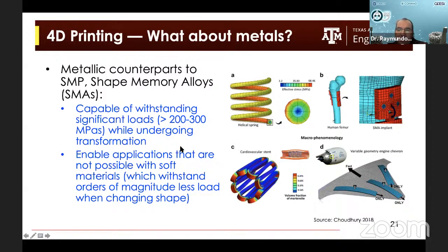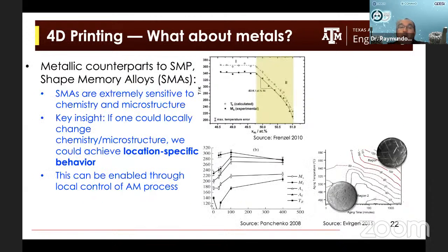Okay. And an interesting thing about shape memory alloys, and the reason why they work actually, is because these are materials that are on the verge of stability. They are barely stable, right? And this is why it's very easy, quote unquote, to move back and forth between one state and the other state. Okay. So these are almost metastable materials, right? They are on the verge of instability. And any material that is almost unstable, or becomes unstable under some conditions, may be very sensitive to chemistry or conformation. This applies to shape memory polymers as well.